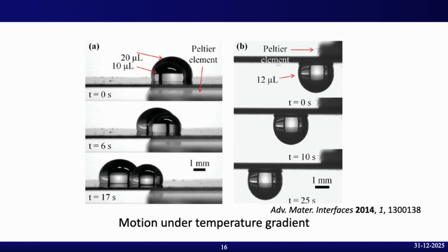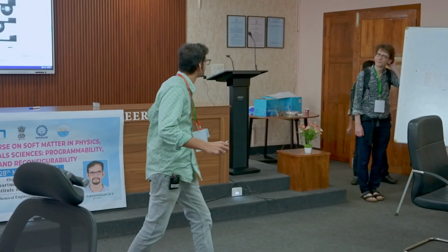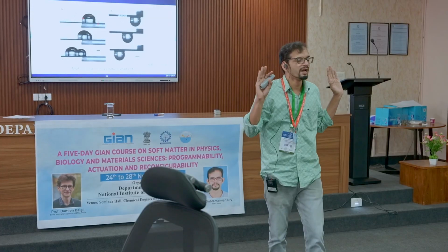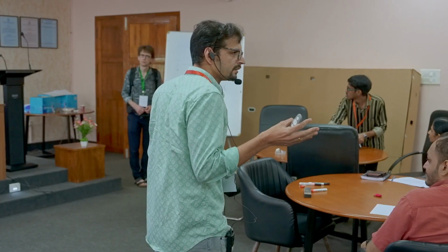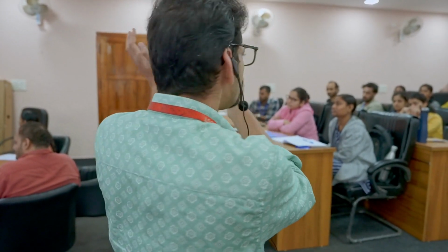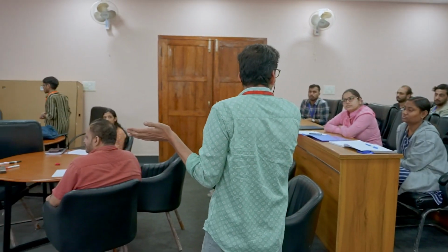This is interesting. Okay? What we did is a very interesting experiment. So you have a slippery, yeah, people will be waiting, I will just finish. You have this slippery surface and you put two droplets having different volume. One is 10 microliter, the other one is 20 microliter. So then I apply a temperature gradient. There is a chance that this oil film itself can move, right? Because there's a liquid form, the Marangoni flow can exist, which we will discuss later. So if it is happening, both the droplets should move in the same velocity, right? But here the elder brother is moving much faster than the younger one, right? Which we believe the opposite should happen, right? Because he can sense the more gradient, right? And it moves. It's interesting.